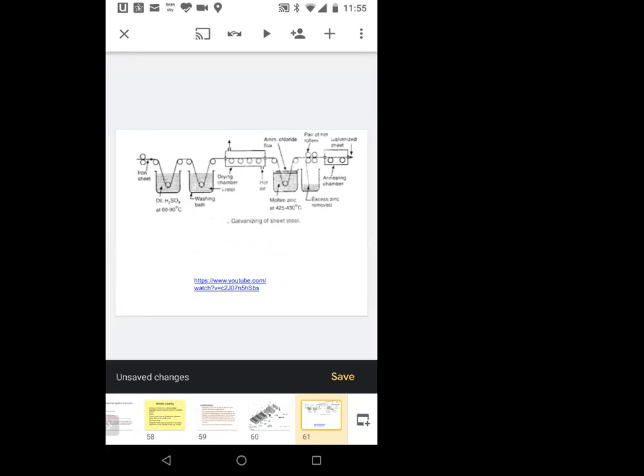First, the iron sheet is cleaned by pickling, by washing the sheets in sulfuric acid, and then it is washed in water so that the surface is cleaned, and then it is dried. After drying, it is passed through the molten zinc, which is kept at 425 to 430 degrees centigrade, so that a thin film of zinc will be coated on it. To avoid further oxidation, it is passed out through ammonium chloride, which acts as a flux, used for avoiding aerial oxidation of the zinc.